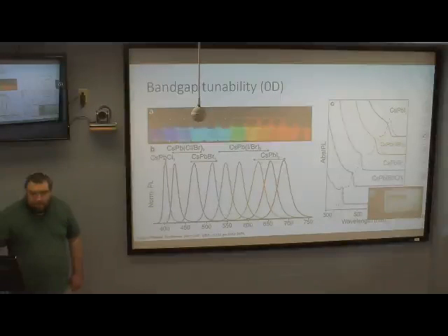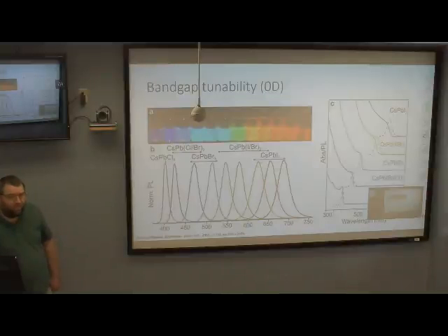So in general, which halide content would be the most optimal for a solar cell? In general, the iodide bromide mix. Yeah, because there's some theory that it's around 700 nanometers, like the optimal. It gives you the best, and it also appears to be one of the more stable ones.